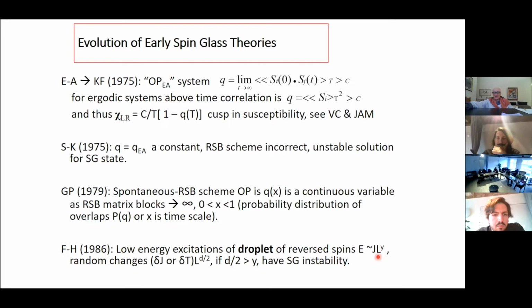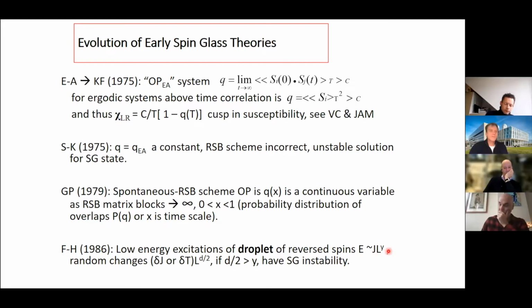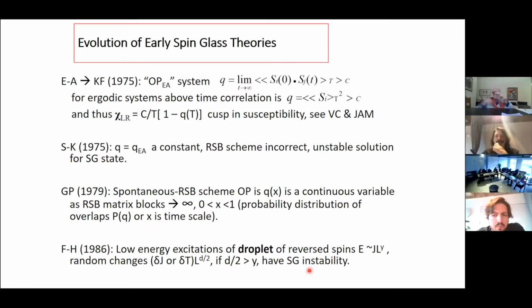And there is a length scale of the droplet, there is the exchange interaction, and there are some critical exponents. Fisher and Huse showed that if these critical exponents have this dimensionality, which gives greater than this exponent here, there is a spin glass instability. In other words, if I have some random changes in my droplet, the droplet expands and quenches the spin glass. You have a spin glass instability. So these theories then give different predictions.